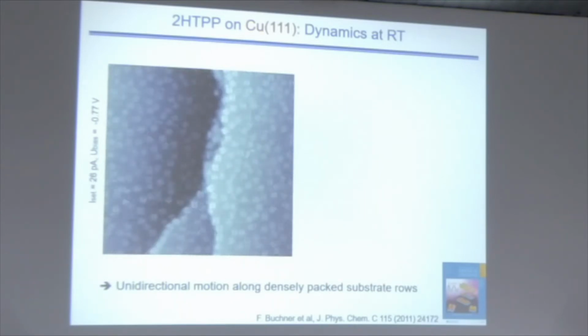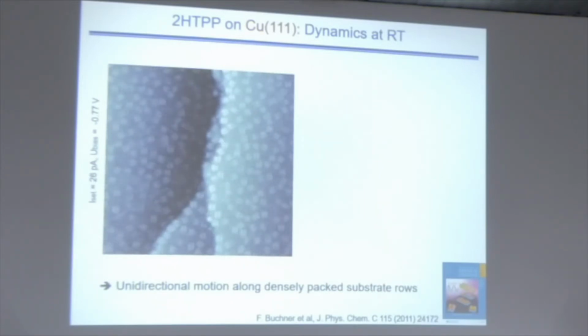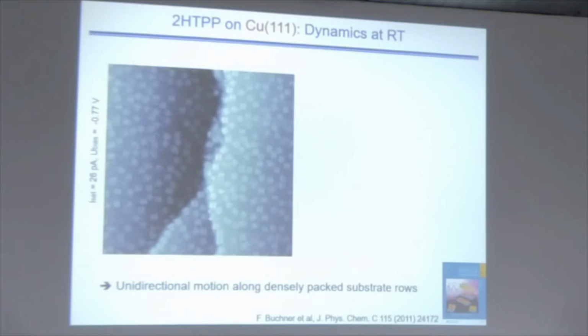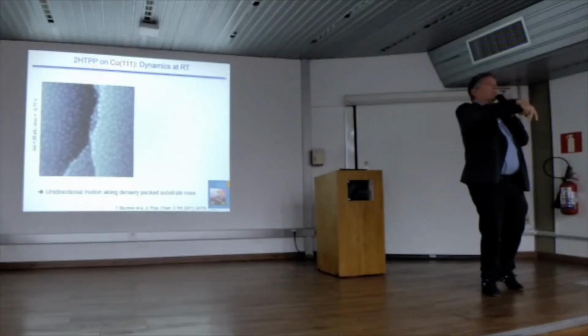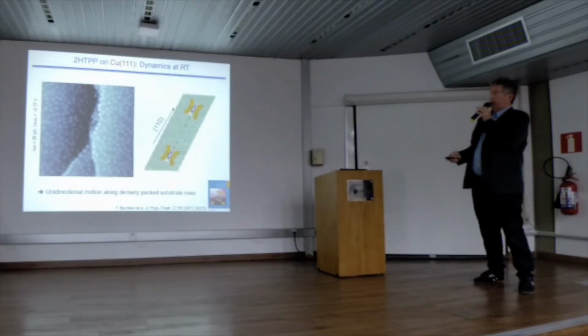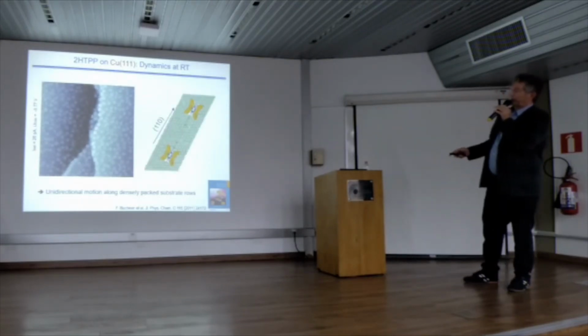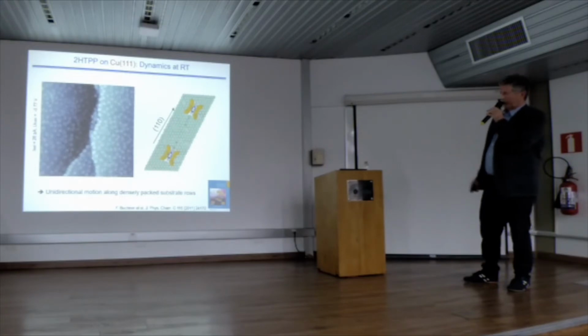We have unidirectional motion along the densely packed rows, and it has to do with the fact you have a covalent bond, and the molecule can hop to a neighboring site with the same covalent type of bond. So this is schematically shown here. They move along the densely packed rows of the substrate, and a 60-degree rotated would be this direction, and minus 60 degree would be movement in this direction.